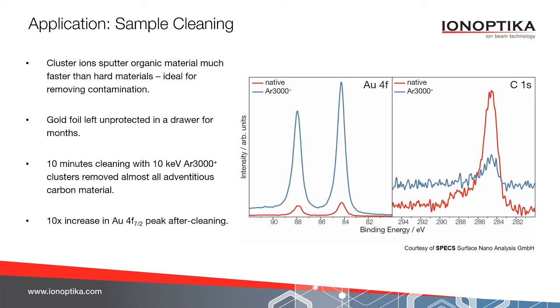This provides a benefit as it means that hard materials can be cleaned of contamination prior to analysis. So for example, here we show a gold foil that was left unprotected in a drawer for several months. Many layers of contamination built up. 10 minutes of sputtering with the GCIB 10S, and we have removed almost all the adventitious carbon material that had built up on that sample.